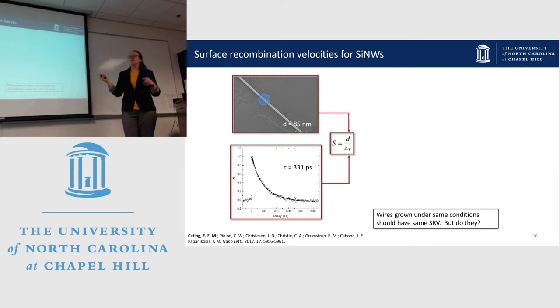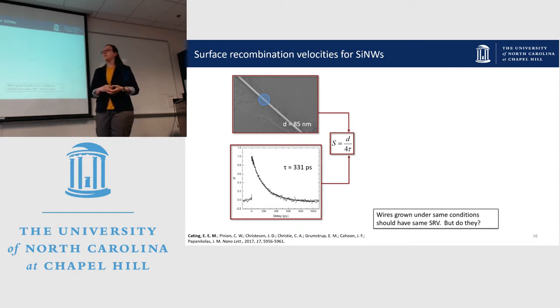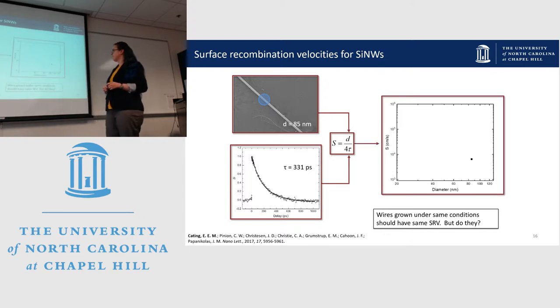So we have this really neat ability to take a wire in our microscope and find that same wire in a scanning electron microscope or in an optical microscope or anywhere else, because we have a registry patterns that we use. So here's an example of this. This is a nanowire. An SEM of a nanowire. This location here is exactly where I took this transient from, right? So we can take the wire to the SEM, measure the diameter. We can take a transient and measure the lifetime, plug it into this expression, and get a value for the surface recombination velocity.